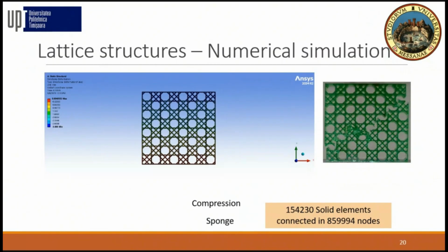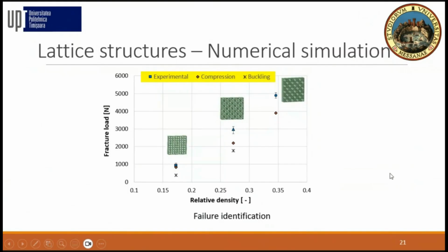So what we try is taking the load from these simulations to compare with our experimental values. I forgot to say, for each test, we use at least four specimens. What we can see here for the triangle, we are very close. The experimental data are these which have the error bar. The others are the simulations. We get the load which corresponds to the maximum principal stress. The lower values here are the buckling. So the buckling is not the main one, it's the first step in damage of these structures, and then either bending or stretching of the struts causes the final fracture.